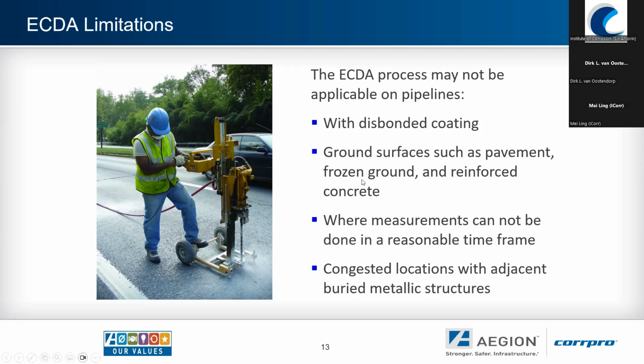However, there are ways to get around that in some cases. For example, in pavement, as we see in the photo, there are possibilities to drill small pilot holes and use those as a means to maintain the contact, but that's not always feasible as well. One of the other big considerations is where the measurements can't be conducted in a reasonable time frame, where there's limitations as to how quickly the different techniques can be conducted on the same pipeline.